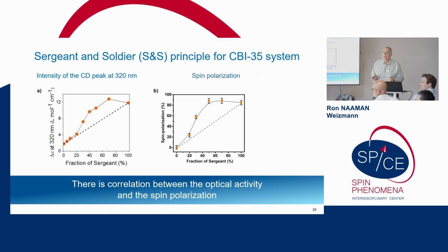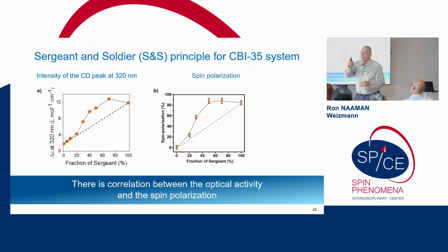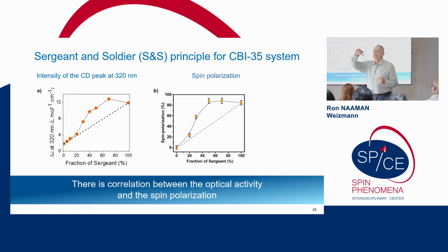Can you explain how you measure the spin polarization getting up to 100% in this tip experiment? Oh, we come with a tip. But where's your spin detector? What? We switch magnetization. We measure the current, the definition is the following. The current when the magnet is pointing up minus the current when the magnet is pointing down over the sum. That's it.